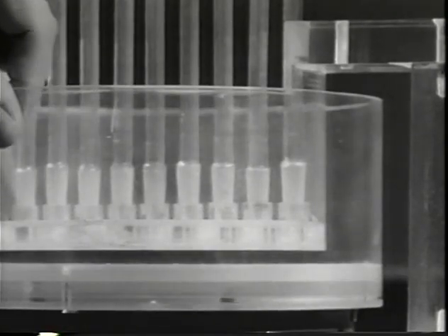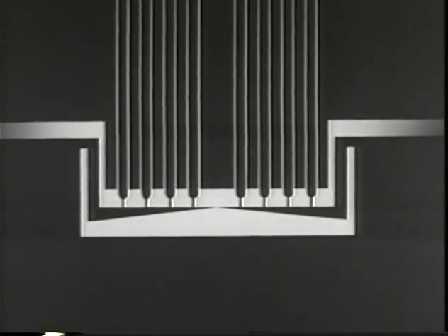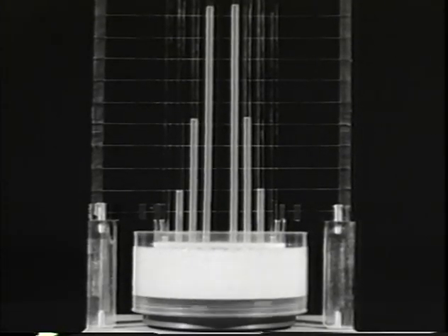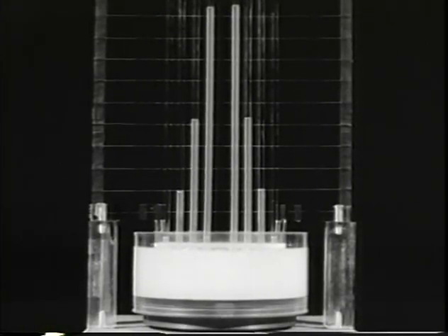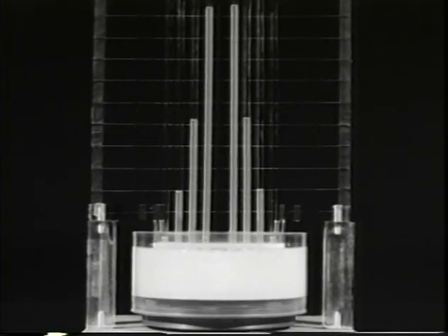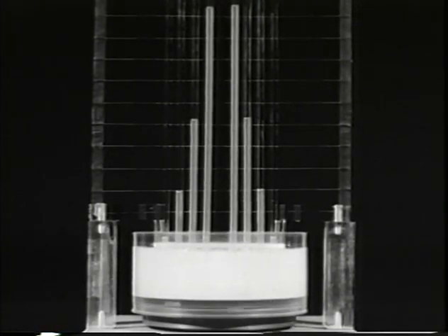If the bottom disk is replaced by a very shallow cone, the stress normal to the stationary disk varies linearly with the logarithm of the distance from the axis of rotation. This logarithmic relation is expected for all memory fluids. These normal stress effects come directly from the non-linearity in the stress-deformation relation.